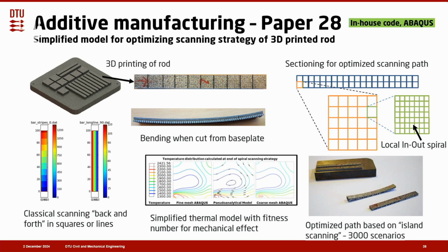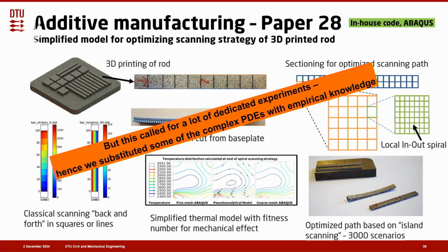And that was because we could optimize. Not surprisingly, the optimized scanning path was scan a little here, scan a little here, scan a little there, which is called island scanning, because then they can shrink independently instead of one long rod that shrinks like this. So it was not a surprising result, but it was even so a very interesting result. But this called for a lot of dedicated experiments, so it's not a general procedure, you could say.